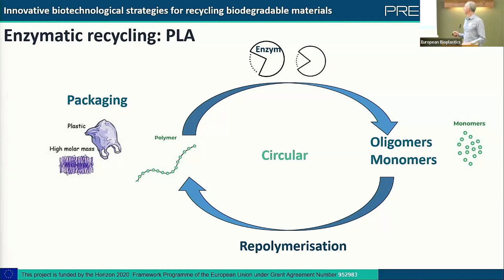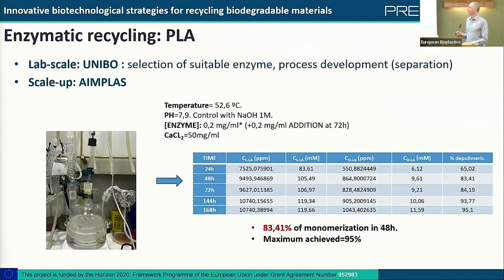So it's all simple on a graph, but in reality, it was much more complex. Unibo did a lot of work on the selection of the suitable enzymes. Enzymes work a little bit as a key-lock system, so the substrate must really fit the enzyme to degrade the material well. And there's also a lot of process development needed to separate the oligomers and monomers from the mixtures. But all this work was quite successful at the end, and Aimplas was responsible for the scale-up then of this process.